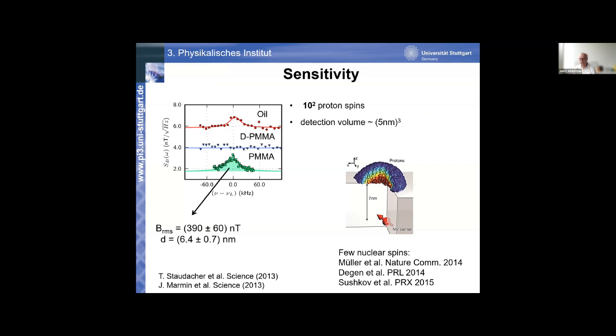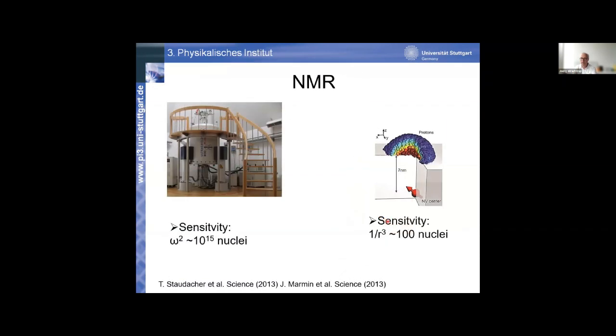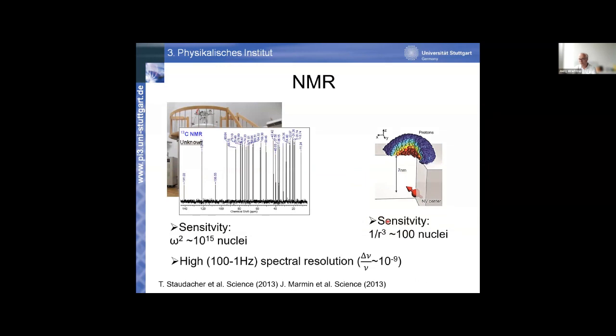If you want to stay at room temperature, it's limited to milliseconds, and that means kilohertz, which essentially means that the local oscillator we are using has a frequency width of a kilohertz, and so you will never be able to resolve hertz signals, because your signal is always a convolution of your local oscillator signal and the external signal. And your local oscillator signal is a kilohertz wide. You never see hertz lines. So it's an intrinsic problem of the sensor that we are not able to achieve hertz line width to begin with.